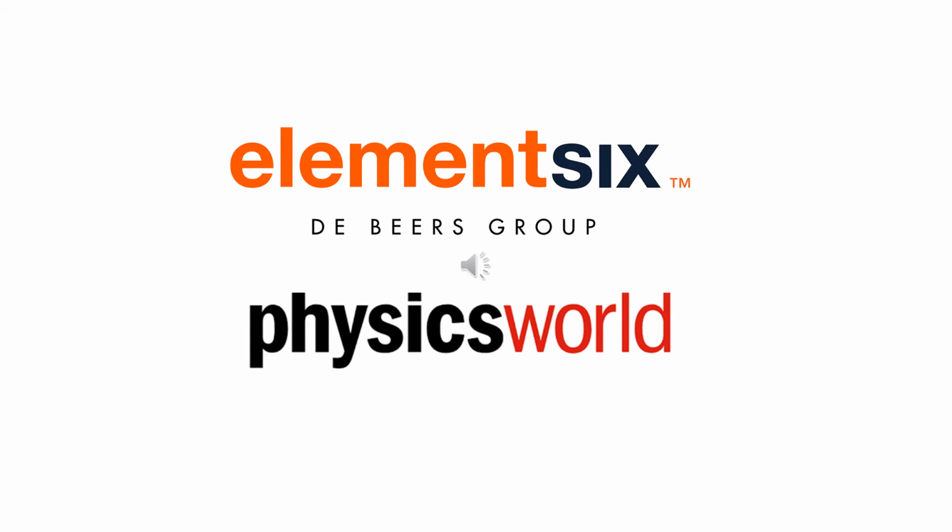So Element 6 at its heart is about growing and engineering extreme materials. And within our framework of materials, it's diamond, it's cubic boron nitride, and it's tungsten carbide, of which most of my work is around diamond. And that means developing the growth processes for doing it, how we grow diamond. And we typically have two ways of growing diamond. One is high pressure, high temperature, which simulates how the earth grows diamonds, putting graphite under high temperatures and pressures. And the second is really what most of what I've talked about today, chemical vapor deposition.